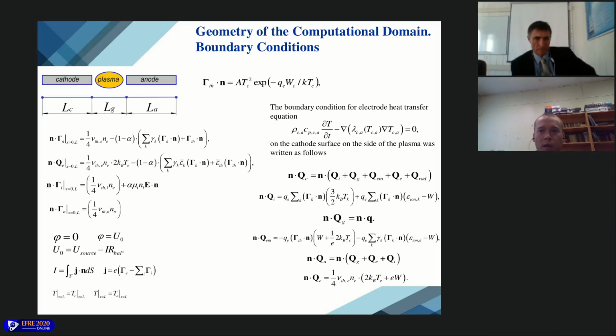The third term corresponds to the energy flow from the cathode surface, determined by the energy expended on both secondary and thermionic emissions. It is worth noting that a part of the electrons that leave the cathode during the emission, caused by elastic collisions with neutral gas particles, can change the direction of their movement to the opposite. At the same time, if their energy is sufficient to reach the surface of the cathode, they will increase the heating. The flow density of energy of backward electrons in this case is given by this formula.